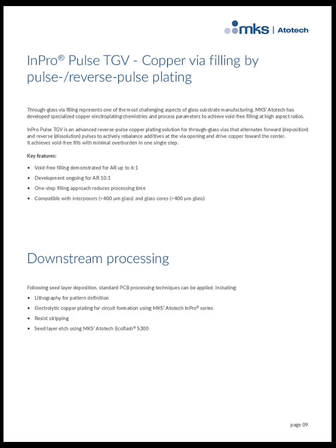Filling through glass vias is one of the toughest challenges. The InPro Pulse TGV process uses pulse and reverse pulse plating to balance additives and direct copper deposition toward the via center, achieving void-free fills with minimal overburden in a single step. This technique currently supports aspect ratios up to 6:1, with development ongoing for higher ratios. After metallization, standard downstream PCB processes like lithography, electrolytic plating, resist stripping, and seed layer etching can be applied seamlessly, enabling full circuit formation on glass substrates.